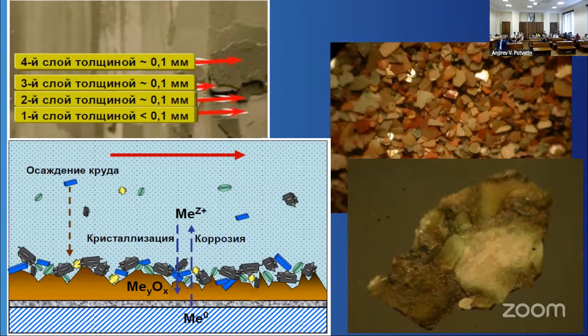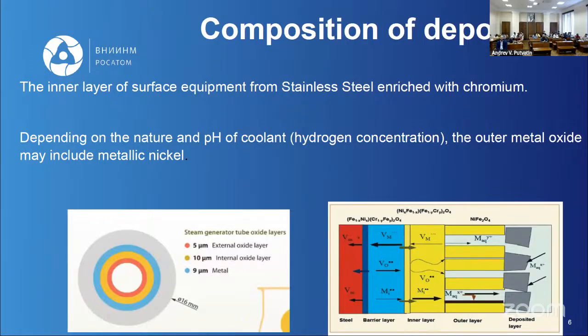So for removal of contaminations, we need to remove all these layers, because contaminations usually accumulate on the surface of metal and are incorporated into the oxide layers, because oxide layers are very good sorbents. So they accumulate all the contaminations inside the environment. And you see it looks like a multi-layer cake.